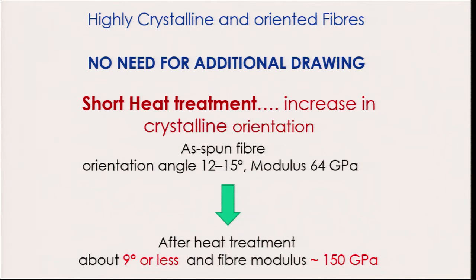and we notice that the modulus increases from 64 GPa to 150 GPa, almost 3 times, very high increase, and this is possible because there is a change in the fiber structure. The orientation angle changes from 12 to 15 degrees to 9 degrees or less. So, imagine a very short heat treatment for a few seconds can result in such a high change in orientation.